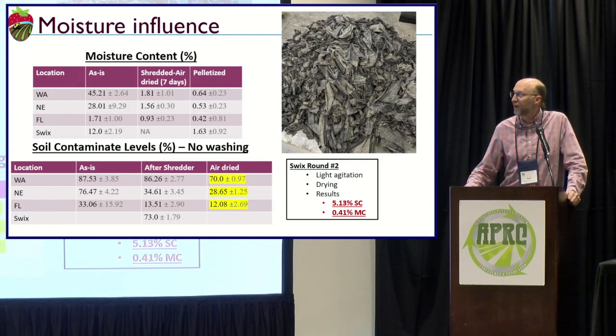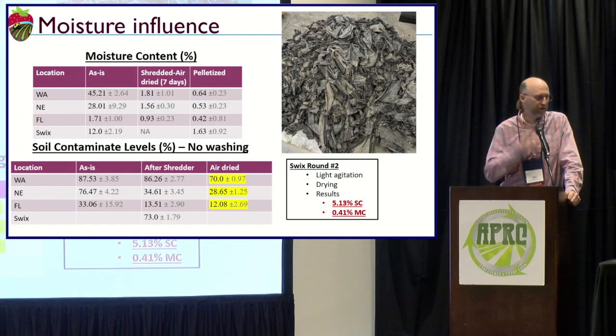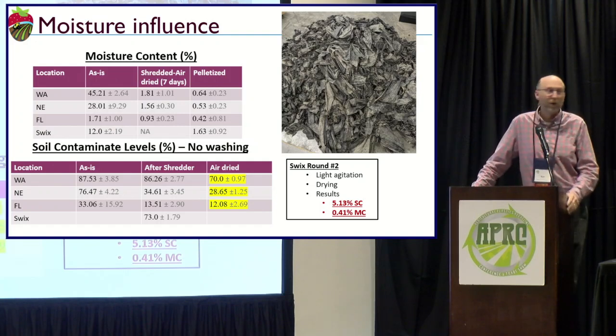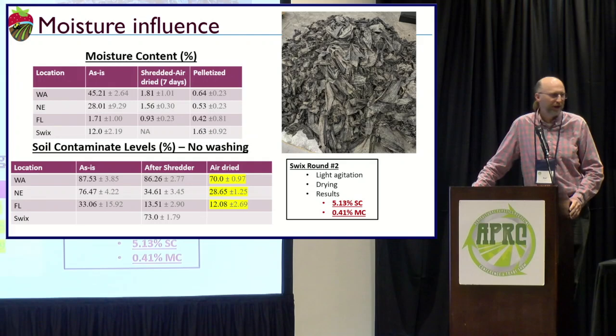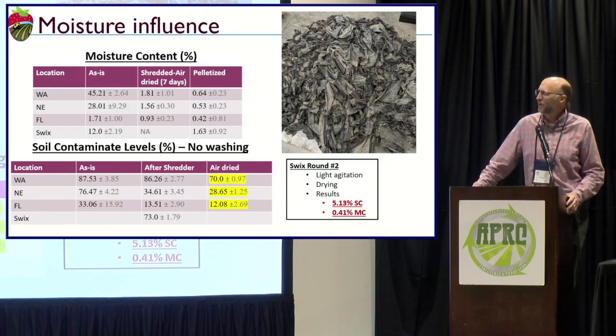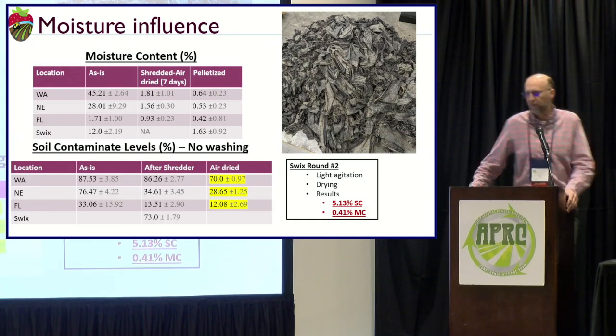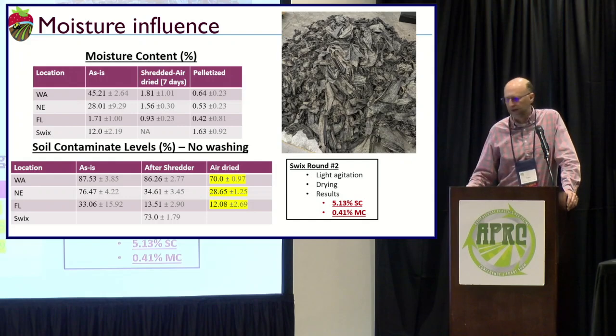When we were up in Mount Vernon, Washington, collecting this material, it was pretty wet out. When we harvested it, it was raining, or it had recently rained. It was typical Washington October weather. So we ended up getting a pretty high moisture content by the time it got back to our lab, about 45%. When we got the material from Nebraska, it was about 28. And believe it or not, the stuff from Florida was about 1.7. I was just in Tampa the other week, and I never thought Florida got that dry, but evidently it was pretty low at that time.